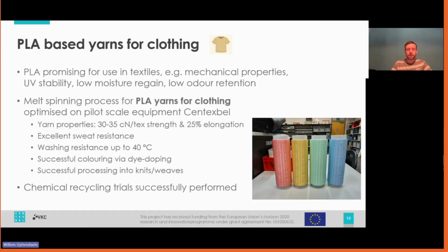And then the final development I want to talk about is clothing. Here, as Lutz mentioned, a lot of clothing is made using polyester. So for that reason, it's quite interesting to look at PLA as a biopolyester as an alternative for the current fossil-based polyester we use now. Of course, PLA is not a drop-in material, so there was quite a bit of work to be done to make sure that the yarns meet the requirements for clothing, such as a strength of 30 to 35 centinewton per tex and good enough elongation.